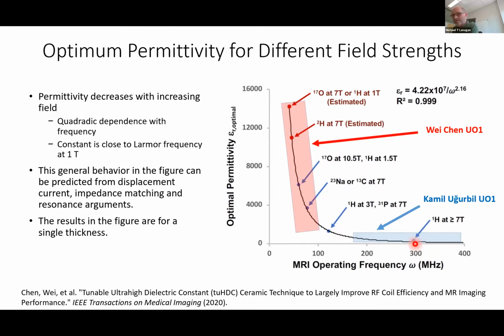The other thing we're looking at are a variety of different X nuclei. So we're looking at oxygen, we're looking at sodium, and we're looking at phosphorus. These are all really interesting if you're looking at, say, for example, ATP and looking at the spectroscopy of what's going on in the body as it's metabolizing. So here we're optimizing for all these different scenarios in terms of the permittivity of the pad. So it's just another way to think about designing these materials around what's needed in the MRI community as we start looking at different X nuclei. As you can also see, though, the permittivity values are getting quite high and the frequencies are getting quite low, and this is getting to be quite a challenge in this range here.